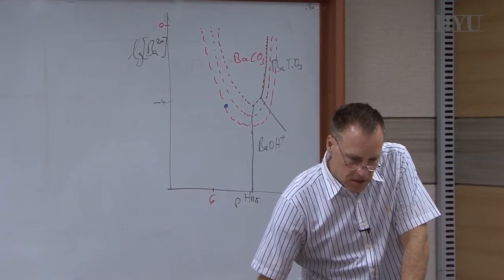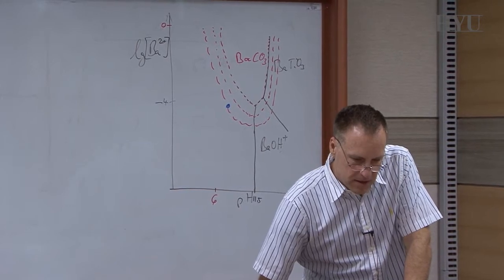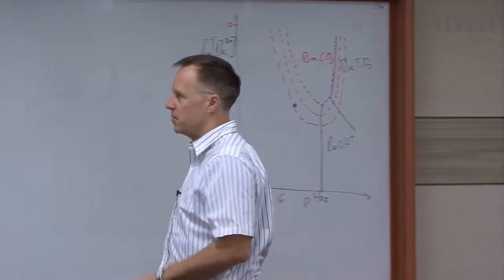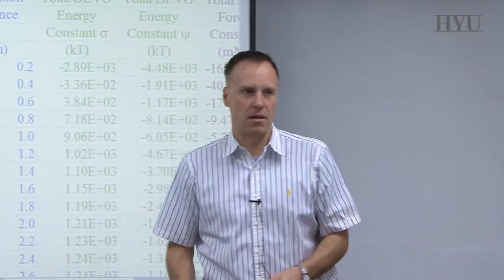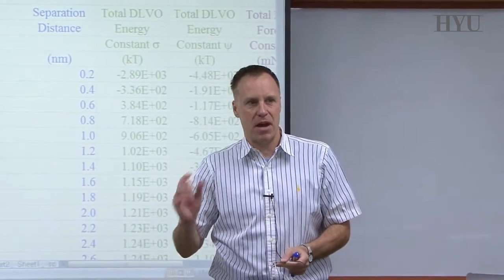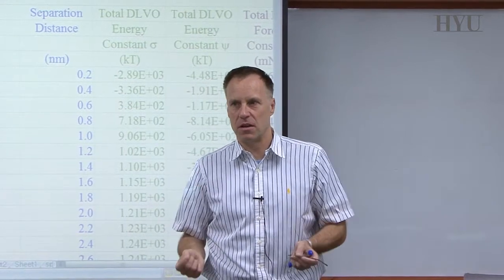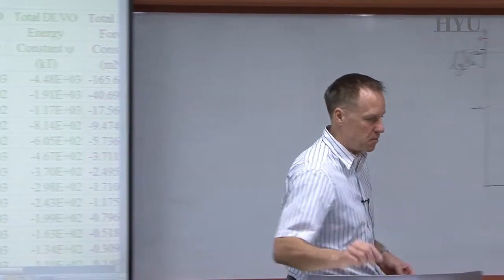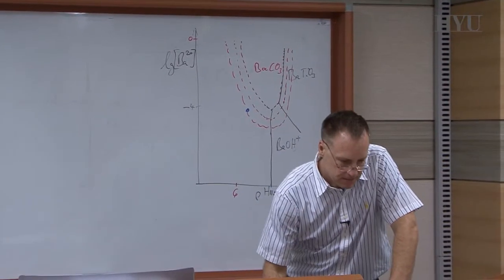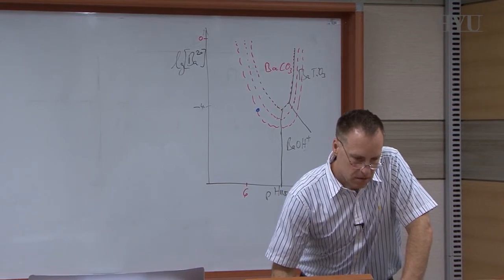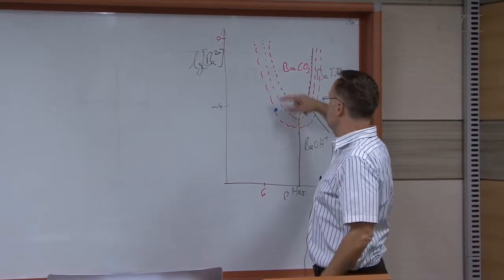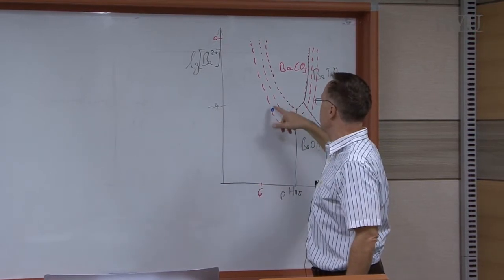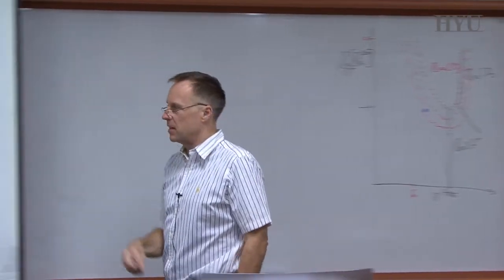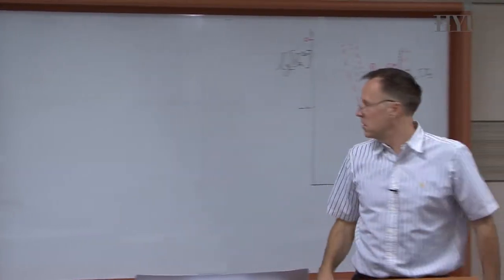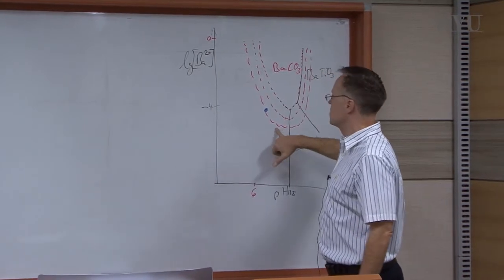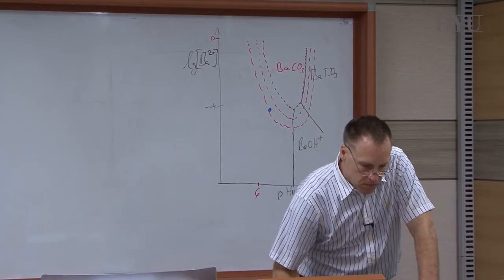Yeah, let's go to this calculation here again. So we have 10 to -4, we have barium ions, and -25 millivolts is a typical number you can achieve on such surfaces. Yeah, so sometimes it's higher, -35, but barium titanate is really difficult to charge on the surface. And there's more details a little bit later why. But if you have this, then you see if you use carbon dioxide that you pump into the system and you work around pH 7, 8, and so on, we basically can stabilize the system. And if you go even further over to pH 9 and so on, you're 10 to -5. So suddenly you can process the material.